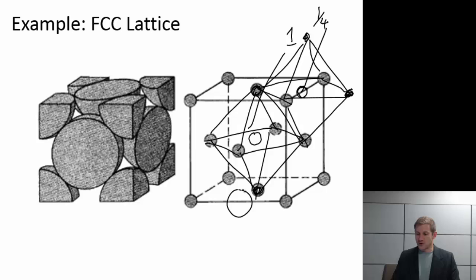So this would be a good chance to identify for yourself where are the rest of the octahedral sites in this lattice. There should be four total. So we count this middle one as one. We count this edge as one quarter. If you identify all the others, it should come up to four octahedral sites.